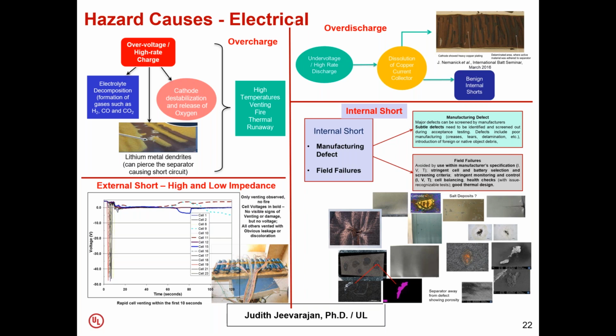I've shown some pictures here of defects that we have found in lithium-ion cells. We've seen iron particles that were not supposed to be there. We've seen tears in the separator, salt deposits. We've seen aluminum left over from tooling, aluminum specks. And then we've also seen some damage to the anode current collector with a hole in it.